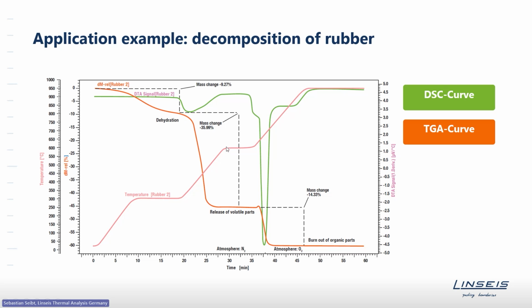Then you have a second heating step where a lot of thermal decomposition takes place. So it's pyrolysis, oxygen-free decomposition, and any organic will be transformed into carbon at that point. And then the atmosphere is changed to oxygen finally, and there's a third heating. During this third heating, all the organics burn off, so you can determine the amount of organics during the third heating segment. And the green curve again shows you the DSC signal. So during these decomposition reactions, you see big endothermic and exothermic peaks, giving you the amount of how much carbon is created, how much carbon is burned off, how much volatiles are released. So that's what a typical experiment may look like.